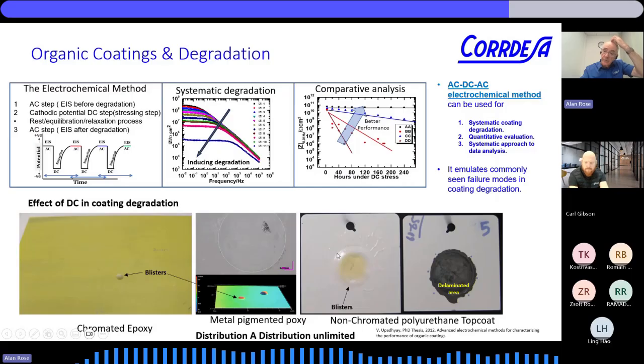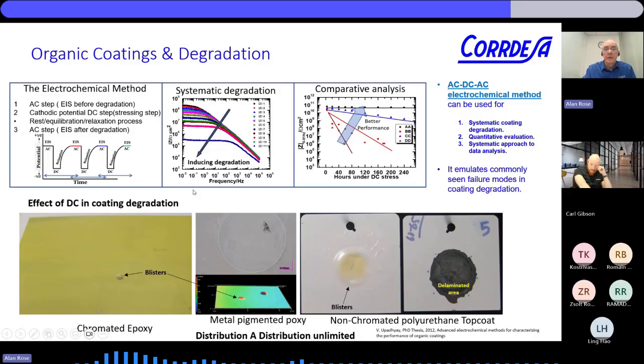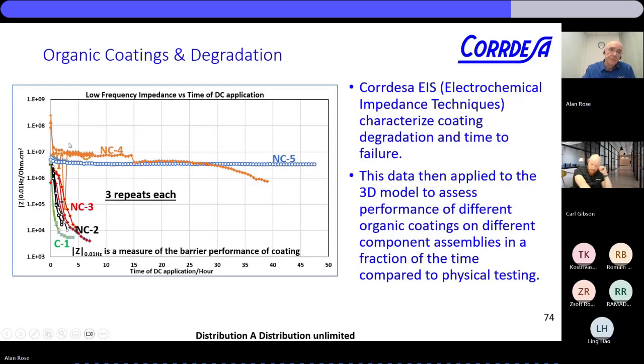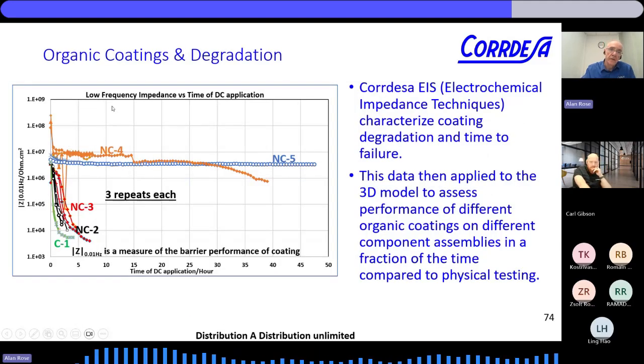And now we're looking at degradation of top coats. We have a technique for acquiring data on organic top coats, and we can insert this experimental data into our model so we can look at the degradation of the top coat, then the ensuing galvanic corrosion of the inorganic coatings underneath.